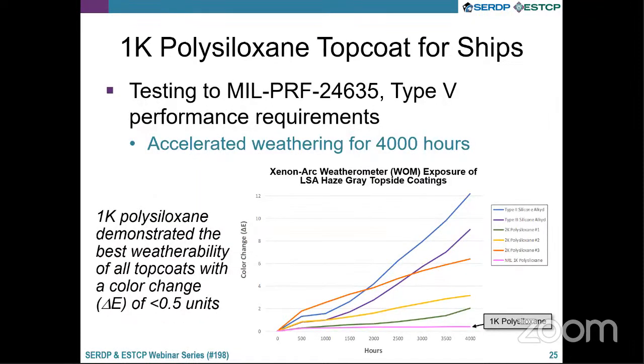And then one of the other tests of many that we had performed early on was to demonstrate the weather resistance of this single component polysiloxane. So what we did was we took 3 of the qualified products from the qualified product list, 3 of the 2 component polysiloxanes from the qualified product list, in addition to 2 of the qualified silicone alkyds, and we exposed them all to 4,000 hours of xenon arc weathering.